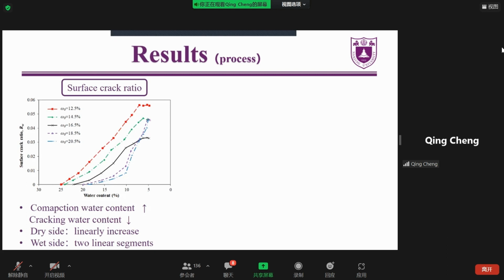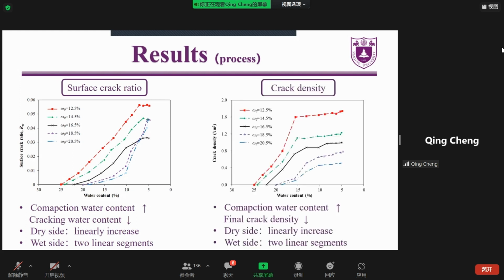The first segment can be corresponding to the initiation of the primary cracks and subcracks. And the second segment corresponds to the widening of existing cracks after the geometric crack pattern tends to stabilize. The evolution of the crack density of each soil sample during the drying process has a similar trend.